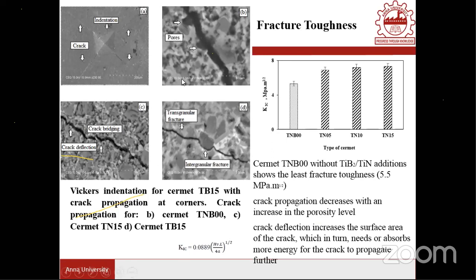On indenting the CERMET surface, there will be a crack emanating from the edges of this indentation. If you look at this first image, there are cracks emanating from the edge of the indentation. We can measure this crack length. If the crack length is really bigger, that means the load is propagating the crack without any disturbance. But if the crack length is lower, that means there is some barrier to crack propagation. So a lower crack length would be more beneficial for improving the toughness value.